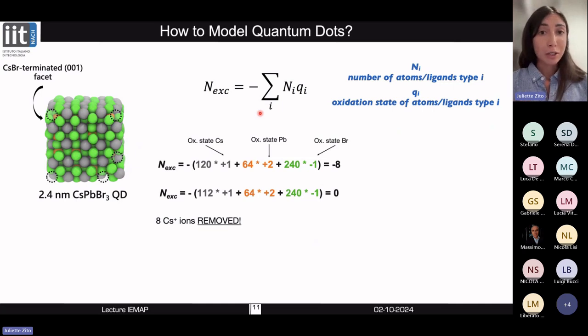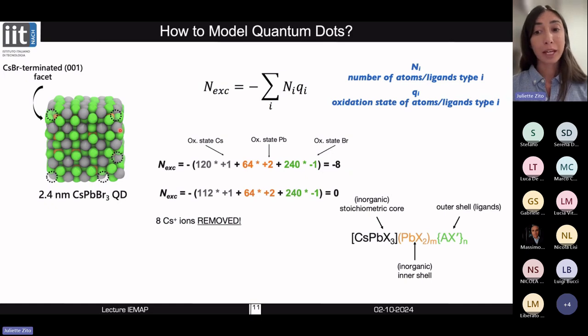Now there is a last thing to check in our model, and this is if our model is charge balanced. This means that if we take the cesium in its more stable oxidation state of +1, the lead in oxidation state +2, and the bromide -1, in the model as cut from the bulk, we obtain an excess of positive charge that has to be balanced by removing 8 positive charges, and in this case, 8 cesium ions from the surface. And here we end up with a charge balanced system